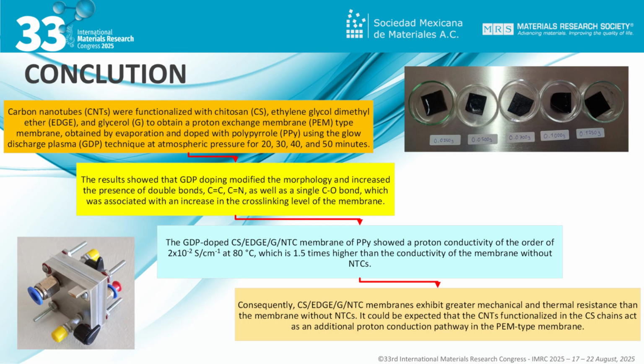Conclusion. Carbon nanotubes were functionalized with Chitosan, ethylene glycol, dimethyl ether, and glycerol to obtain a proton exchange membrane type membrane obtained by evaporation and doped with polypyrrole using the glow discharge plasma technique at atmospheric pressure for 20, 30, 40, and 50 minutes. The results showed that the glow discharge plasma technique doping modified morphology and increased the presence of double bonds, carbon-carbon, carbon-nitrogen, as well as a single carbon-oxygen bond, which was associated with an increase in the cross-linking level of the